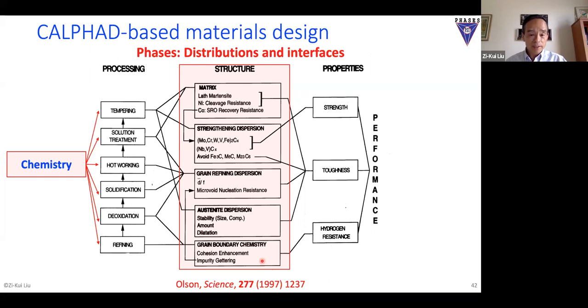Whether coherent - the nickel-based superalloys work well because of coherence of the interface. Same thing with aluminum alloys, you get coherent precipitates. There's the distribution and the phase interfaces - for example, phase field simulation controls the distributions.